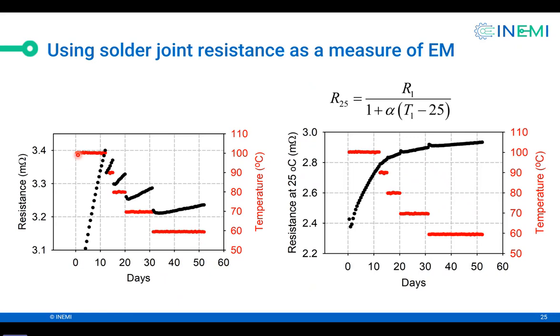So first, we had the oven temperature at about 100 degrees centigrade. Now, this is not the temperature of the solder joint because we have to add the Joule heating. So here I'm just showing you the oven temperature is at 100 degrees and the resistance shoots up and gets to this value. And so we ran this test at 100 degrees for 10 days. And then we lower the temperature to 90 degrees.